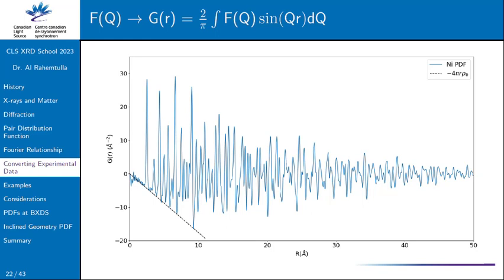And your peak gets broader or narrower. And with the particle size, the signal is going to die at some point. When your particle ends, say you have 20 nanometer gold particles, you will not see any peak beyond 20 nanometers because there are no neighbors farther than that. So your signal dies, and you can easily get nanoparticle size from this technique. I found that really intuitive. Direct space, no confusion with reciprocal space. It's very powerful.